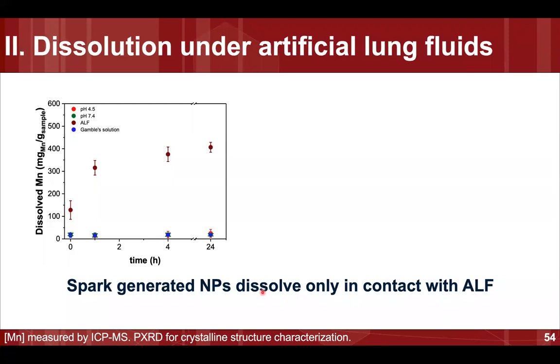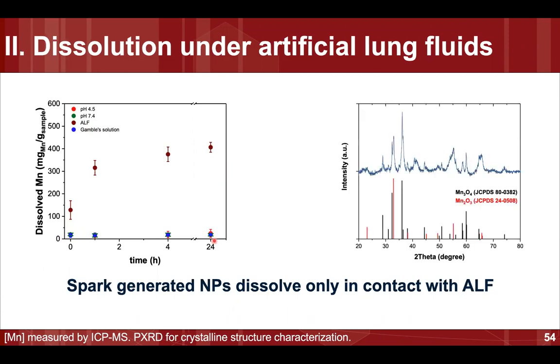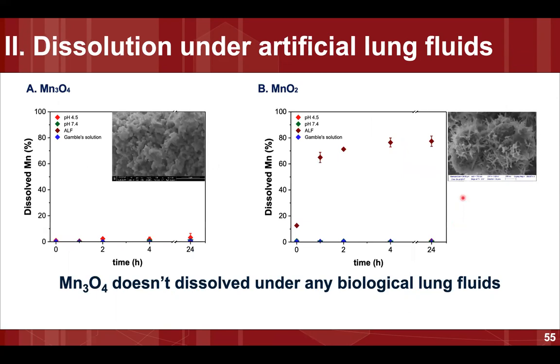physiological conditions, right? And we found that they only dissolve partially in the ALF, that is the macrophage conditions. So that means that if the nanoparticles cross the barrier and go to blood, they will enter our bloodstream. Looking at the tail of these nanoparticles that we generated in this synthesis, we found we have 2 different oxides of manganese. So I wanted to understand which one we were dissolving. And the manganese oxide, manganese 2,3 oxide, doesn't dissolve at all, while the manganese oxide 2, or MnO2, dissolves in these conditions. So that means that depending on the chemical composition of the manganese in the particle, it will dissolve or not.